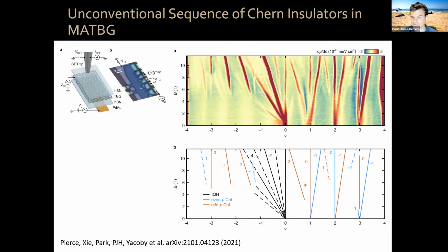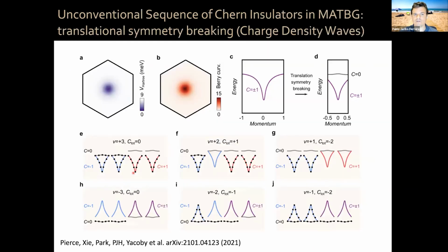Which do not conform: before from 1, we should have a Chern insulator with slope 3, from 2, 1 with 2, which we see here, from 3, 1, 2 with 1, that we see here, but we see plenty of other Chern insulator states. That unconventional sequence of Chern insulators has to do partly with the fact that interactions can give rise to translational symmetry breaking, spontaneously due to interactions, or otherwise the formation of charge density waves in the system.